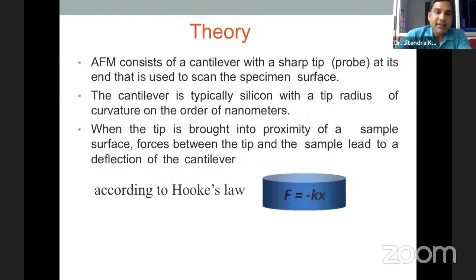This basically consists of a cantilever, and that cantilever carries a very sharp tip. The tip curvature is approximately 25 micron, and the tip is generally made of silicon, which is a very widely used material. When I was doing my doctorate, I tried to replace the silicon tip and fabricate an SU8 tip, because the fabrication is very easy and it is easily curable.